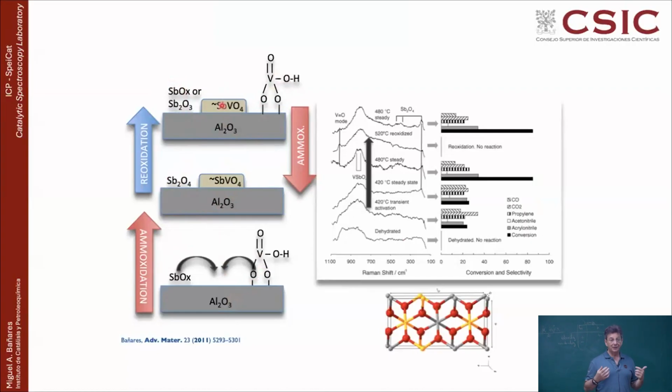If we were looking at different stoichiometries of vanadium antimony, in some catalysts, we have even higher amount of antimony, and in this case, it was interesting because you go from Sb2O4 to Sb2O3. So basically, what happens is that in the end, the amount of segregated antimony decreased, either from Sb2O4 to Sb2O3 or to an amorphous one. This one is apparent in Raman, this one is not apparent in Raman, and you have different bands.